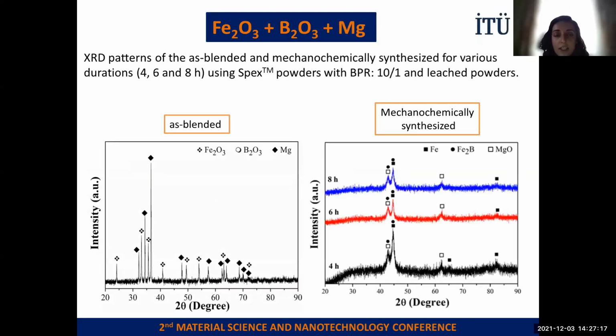And firstly, the first batch, the iron oxide, boron oxide, and magnesium batch. As blended powders, the XRD pattern is clearly seen from the left-hand side, and the peaks belonging to our initial materials are clearly seen in this XRD pattern. After the 4 hour, 6 hour, and 8 hour milling, the XRD peaks belonging to the raw materials were completely removed, and iron boride and magnesium oxide peaks were clearly seen after the milling.